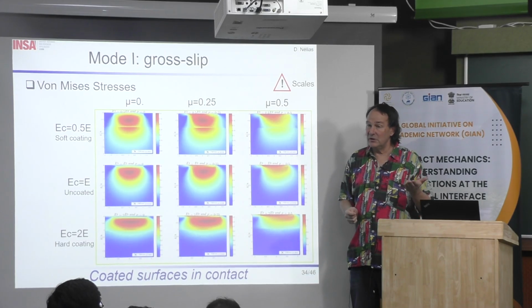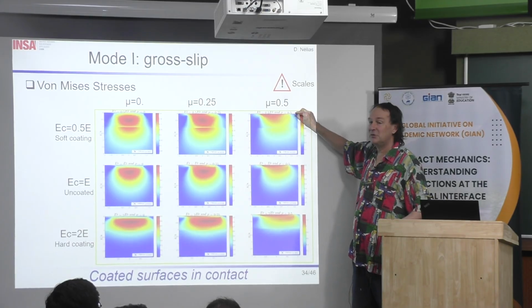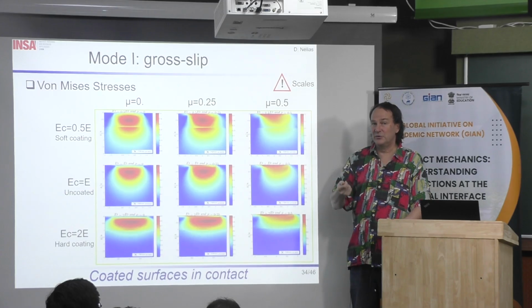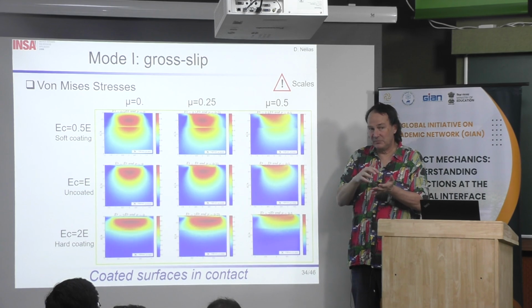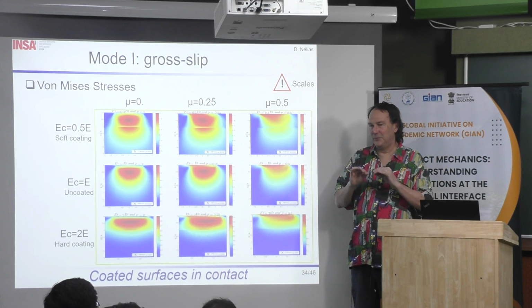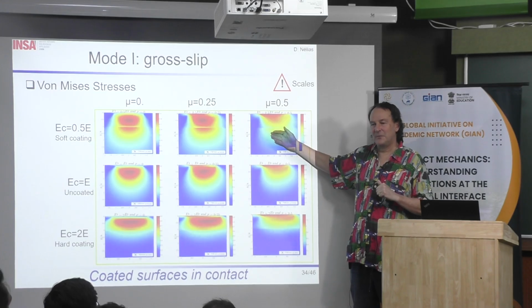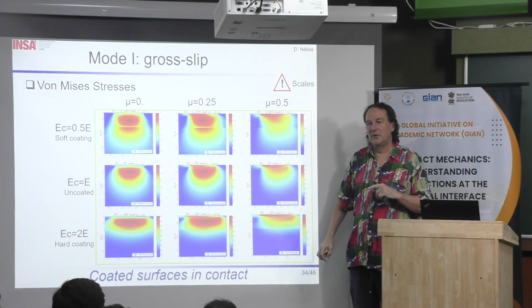And the second solution is to have a very, very thin coating, very, very thin. Because it will act, for example, on the friction, on the boundary lubrication, when you have contact between asperities. And because it is very, very thin, it is not detrimental for that. Less than 1 micrometer, typically.